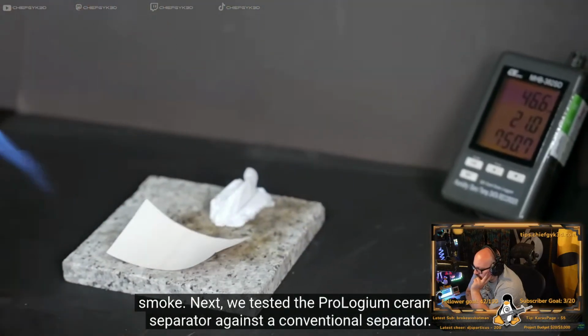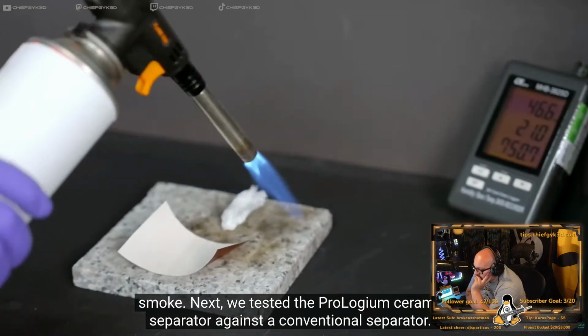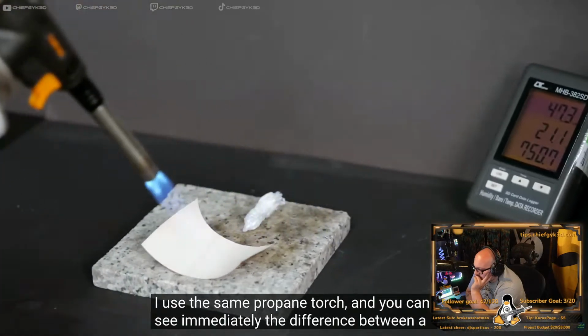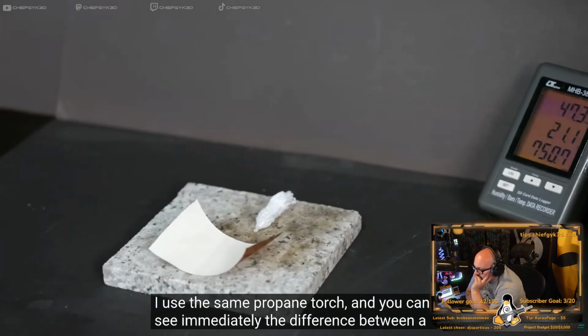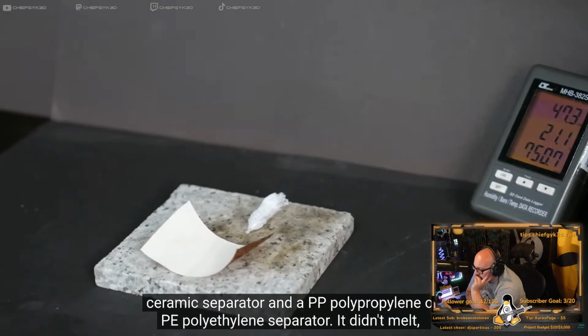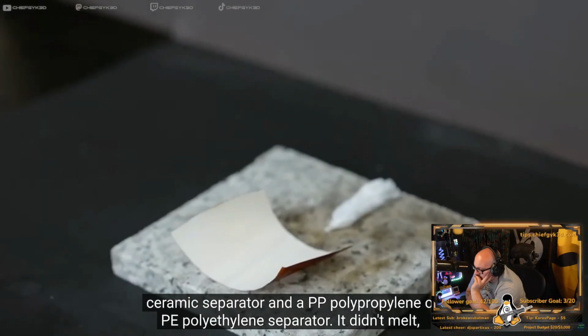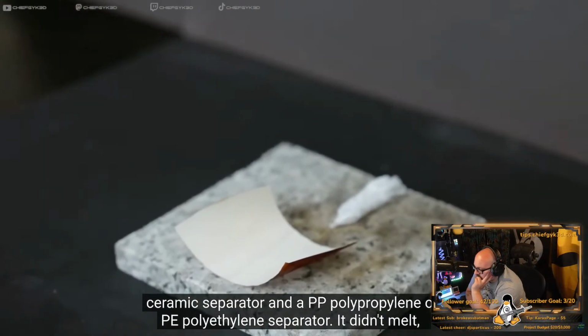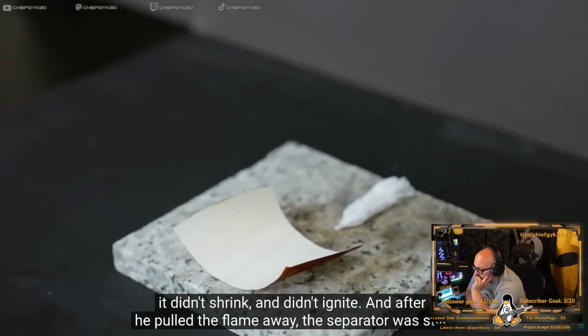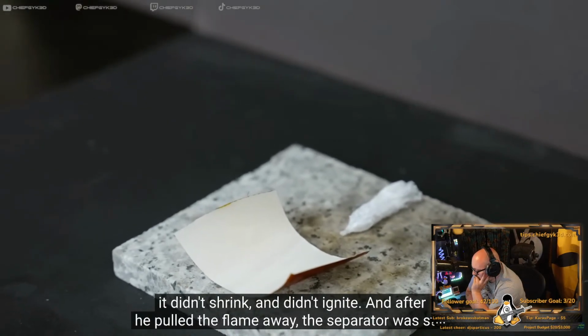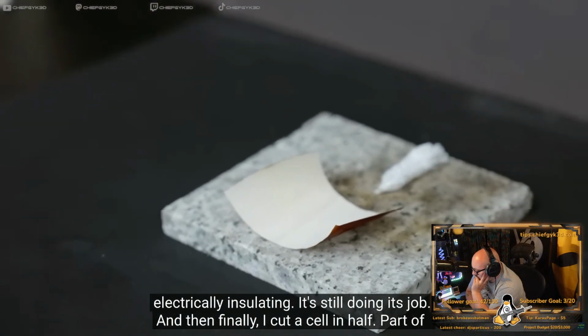Next, we tested the ProLogium ceramic separator against a conventional separator. I used the same propane torch, and you can see immediately the difference between a ceramic separator and a PP polypropylene or PE polyethylene separator. It didn't melt, it didn't shrink, and it didn't ignite. And after we pulled the flame away, the separator was still electrically insulating.